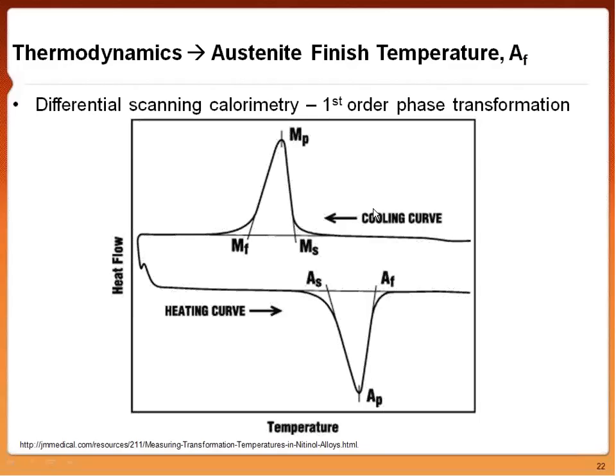But if you see the curve here, we go on the cooling curve. When we transform from austenite to martensite, we have heat release, heat flow out of the system, and we can monitor the same on this curve. When we go from martensite to austenite, we have heat absorption.